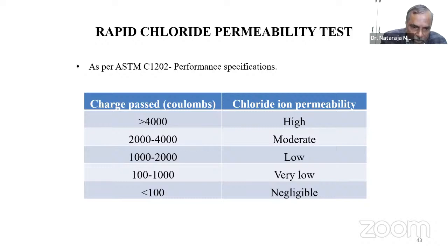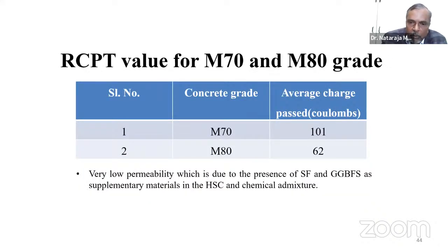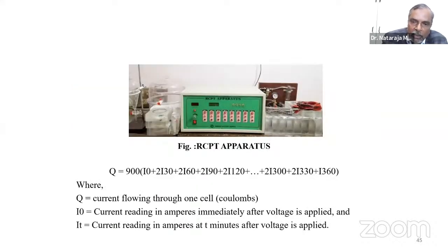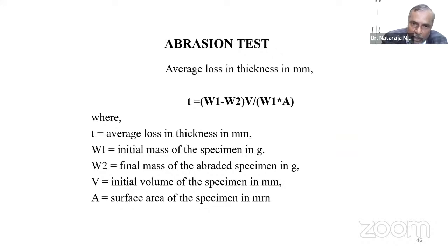And this is the range, as you can see here. But any concrete, if you test it, will be very close to 1000 to 2000, indicating that the permeability is low to moderate. But because we are using a higher percentage of supplementary materials, and also because of adding silica fume, our RCPT value is coming very close to 62 to 100, indicating that it is a highly impervious concrete.